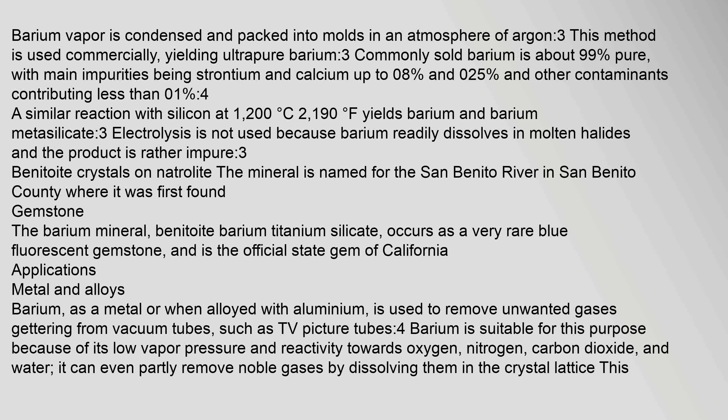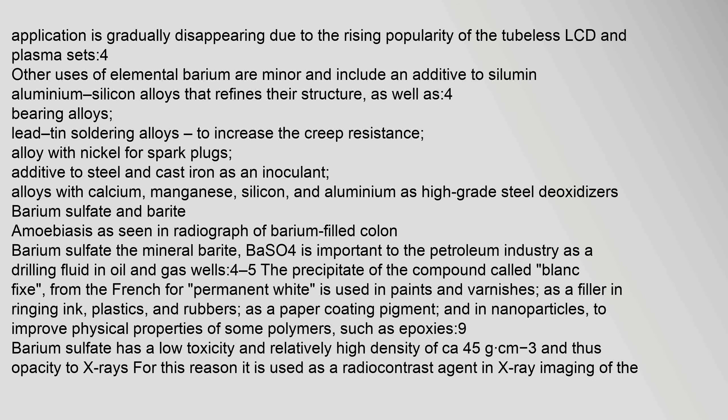Commonly sold barium is about 99 percent pure, with main impurities being strontium and calcium. Other uses of elemental barium include: an additive to silicon-aluminium alloys that refines their structure, bearing alloys, lead-tin soldering alloys to increase creep resistance, alloys with nickel for spark plugs, additive to steel and cast iron as an inoculant, and alloys with calcium, manganese, silicon, and aluminium as high-grade steel deoxidizers.